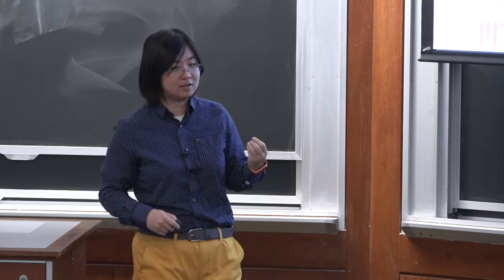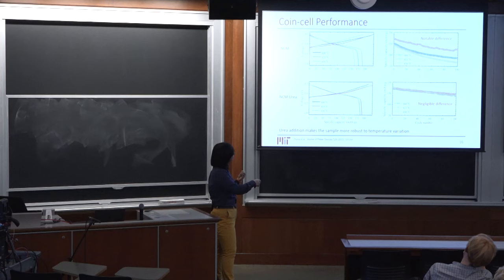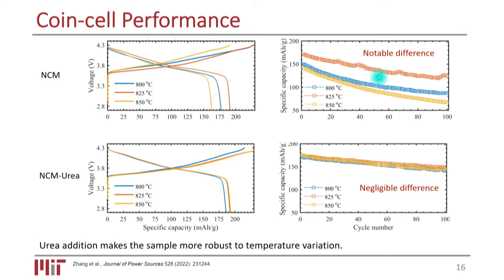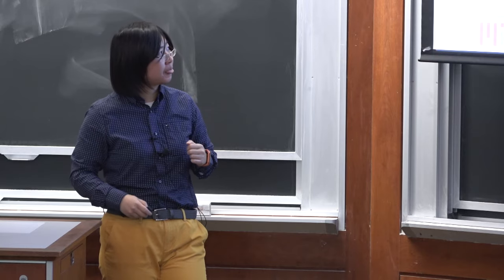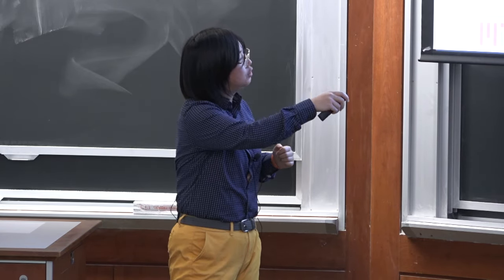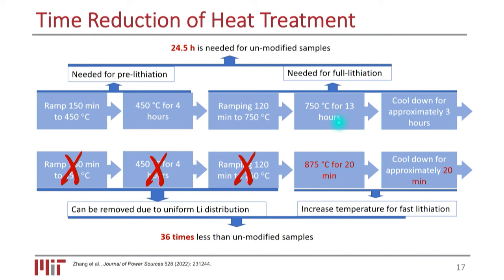And why having higher thermal stability is good is that in the previous one, it's super sensitive to the temperature, and if we increase the temperature too high, we will not have good performance. And that's why we need to calcinate the material at a relatively lower temperature of 750 and for 13 hours long. However, by adding urea, this material can sustain higher temperature. So by increasing the temperature, we can significantly shorten the calcination time, and that is the goal. So previously, like I mentioned, we need to follow the recipe for co-precipitation, that's the 750 for 13 hours, but that's not the entire story.